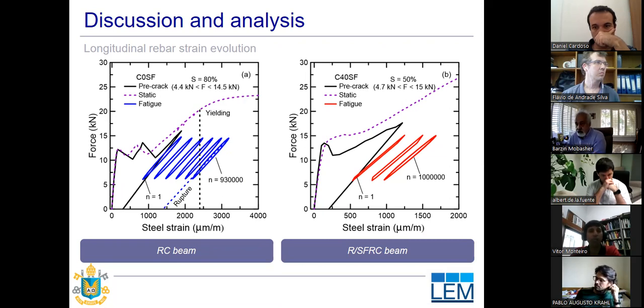It's possible to see that both beams were subjected to the same loading range, from approximately 4.5 to 15 kilonewtons. So without the use of fibers, the beam reached rupture and presented a major evolution in the rebar strain under fatigue. The addition of fibers is responsible for redistributing the stresses around the tension zone and mitigating the rebar strain evolution along the fatigue.